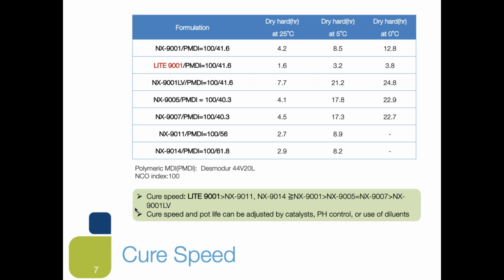We also measured cure speed of each polyol, curing with the polymeric MDI in this case. So we measured dry hard time at different temperatures, some as low as 5 degrees C and 0 degrees C. In this study, we identified that LITE 9001 is the product that offers the fastest cure speed.